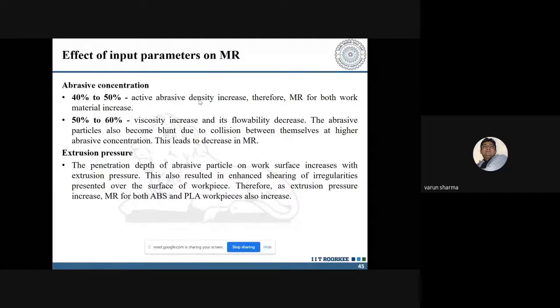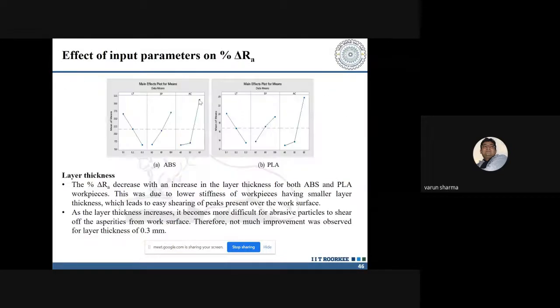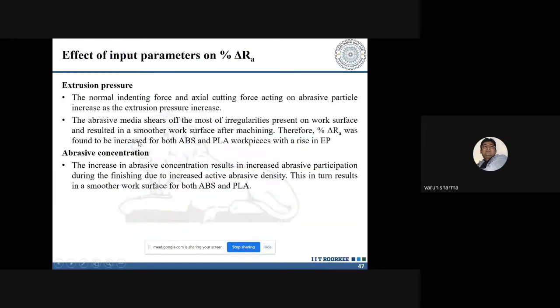Now, the extrusion pressure was directly proportional to your axial force. So if I increase my extrusion pressure, my axial force will increase in a similar manner. Now, similar trends were achieved for the input parameters on percentage del Ra. What we found from this is that there was more scope for material removal. However, there was not much improvement for the 0.3 mm layer thickness.